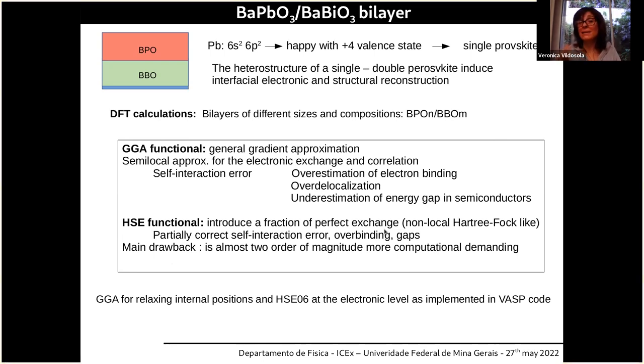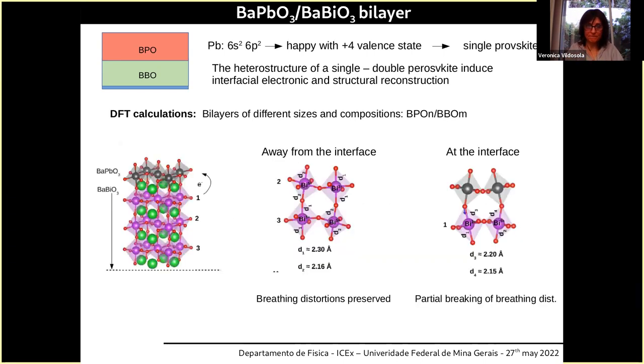That is what we made with our colleagues. We made some studies to analyze that we can safely treat the structural relaxation of the material at the GGA level, and only apply this hybrid functional at the electronic level. We checked it on the bulk situation, and we apply this methodology to the bilayer.